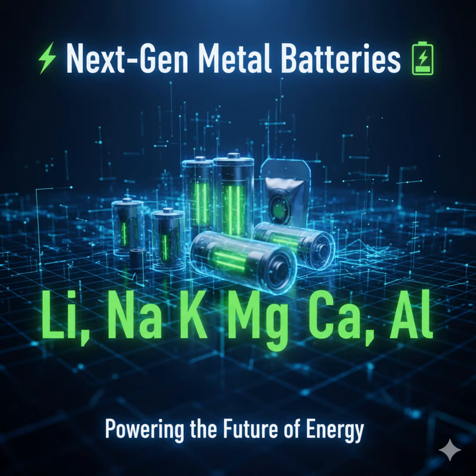Inorganic. That sounds tougher than the organic mess, like maybe a ceramic tile instead of wet tissue. It is generally much tougher mechanically. But here's the crippling problem. This inorganic-rich SEI formed by multivalents is often ion insulating. But the ions need to get through. The bouncer isn't just keeping electrons out, it's blocking the ions too. Precisely. It forms this hard, dense, inorganic wall that completely passivates the anode. The ions hit this wall and just stop. The reaction grinds to a halt.